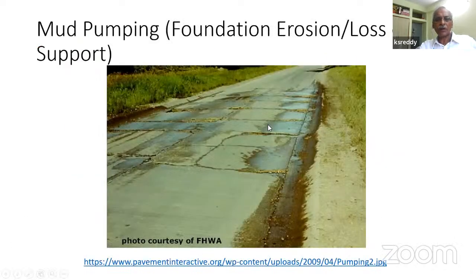This is the failure of foundation. The foundation layers are getting eroded and coming through these cracks and joints getting deposited. So since there's a mud that is getting deposited, we call it also as mud pumping. But basically, this is the loss of support, especially if you got fine material there in the foundation. And if it is wet, you are subjecting those slabs to application of heavy loads, and there is a pumping action. So you can expect pumping of fines happening from the foundation layers.